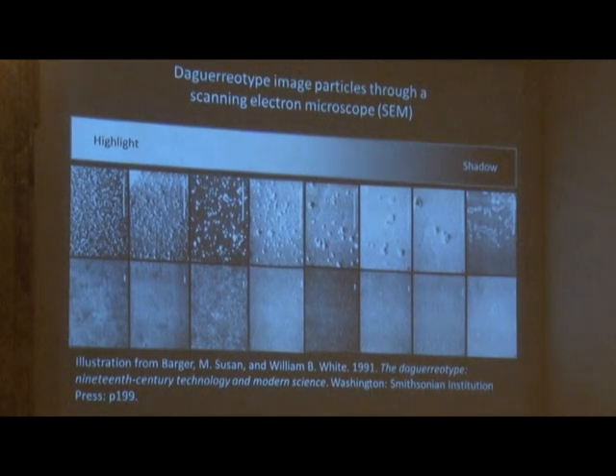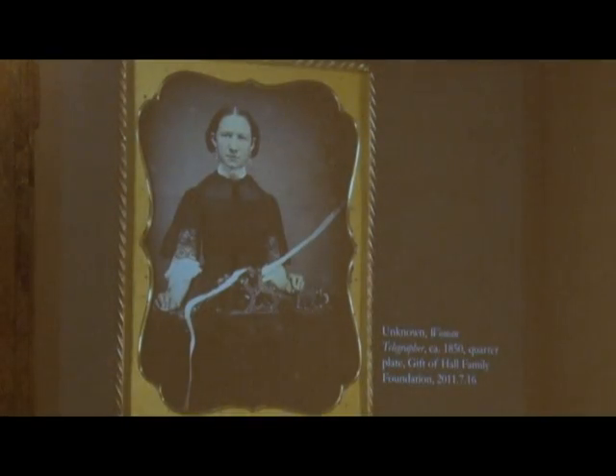These image particles are 0.1 to 1 micron in diameter. To give you a point of reference, human hair is about 40 to 120 microns in thickness. So they're about 100 times smaller than the thickness of our hair. Very tiny. And that is precisely why daguerreotype images can be so sharp.